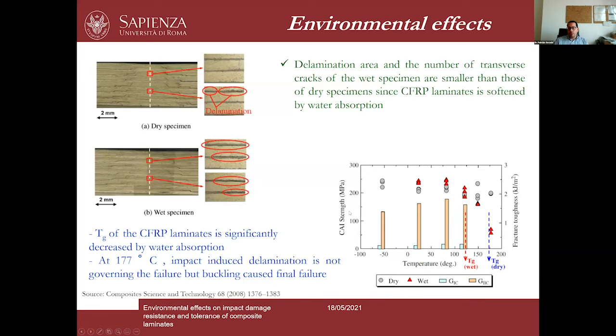Okay, and this is clearly seen in this picture here. In this picture, we have the compression after impact strength as a function of temperature, because usually when you have an impacted sample, if you want to measure the damage tolerance of this composite material, you can easily perform a compression after impact test. And if we look at this table and this graph in this specific case, we can see that if we perform the compression after impact test at pretty low temperature, we can say up to 100 Celsius degrees, there is no significant difference between the strength retention of the dry and wet specimens. The situation is completely changed at high temperature. So in particular, in this specific case, the authors performed the compression after impact test at 177 Celsius degrees.